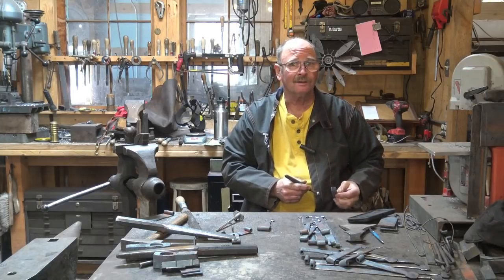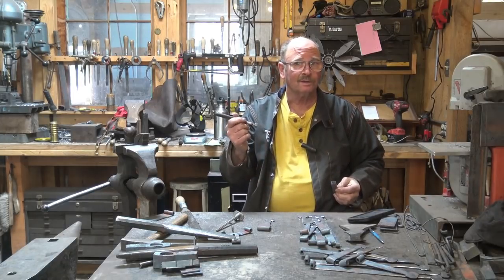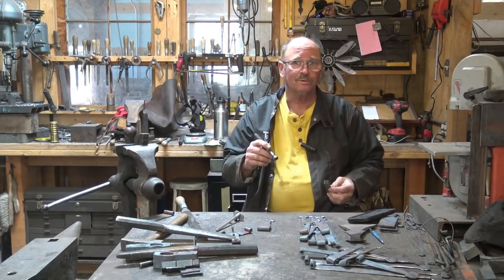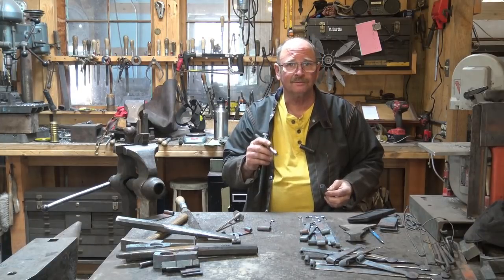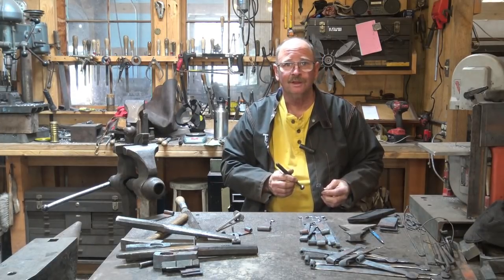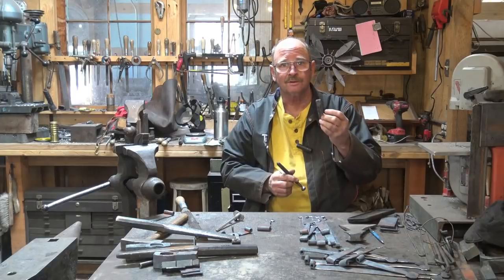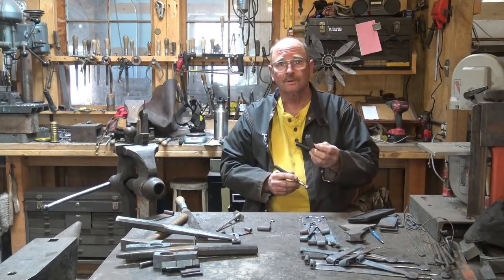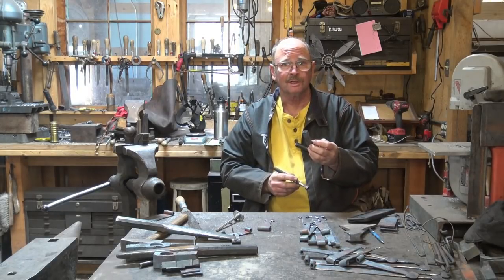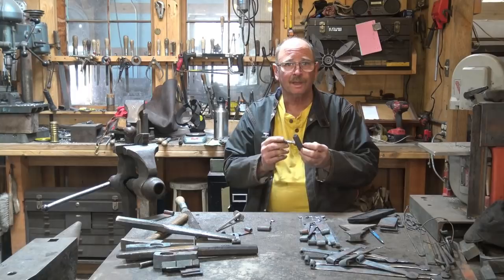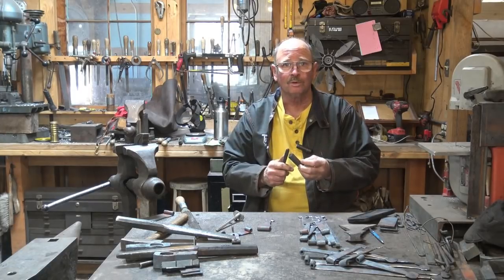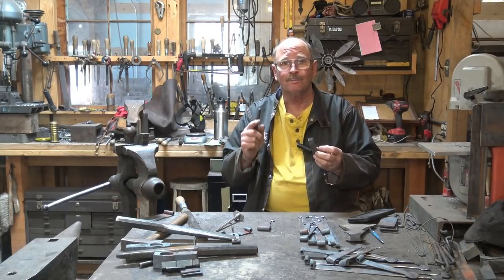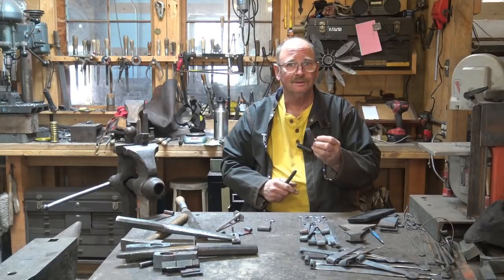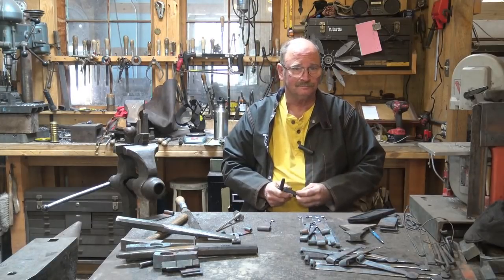One way to find that out is let's do a test. I've got that brand new heat treat oven with a very precise temperature control on it, and this is a good way to do this test. So I'm going to put all this stuff in the heat treat oven. I'm going to bring it up short of critical temperature to start with. I think I'll bring it up to maybe 1200 or 1400 to start with, and then we'll see if it's still magnetic, and then we'll bring it up a little bit more and see where it loses it, and then compare some of the other steels and see how they did.